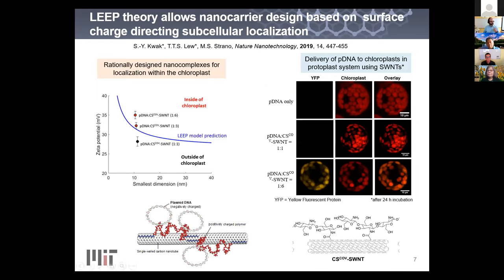This is a carbon nanotube wrapped in chitosan, and we've complexed it with a plasmid DNA. And you can see here, if you apply LEEP, you can adjust the charge by changing the pDNA to chitosan ratio, and LEEP is spot on, meaning that when the charge brings the complex down to this one to one, we see no yellow fluorescent protein in the chloroplast. But if you increase the charge, you see the expression, and it follows exactly the theory. The deterministic nature of this equation continues to be amazing to me.